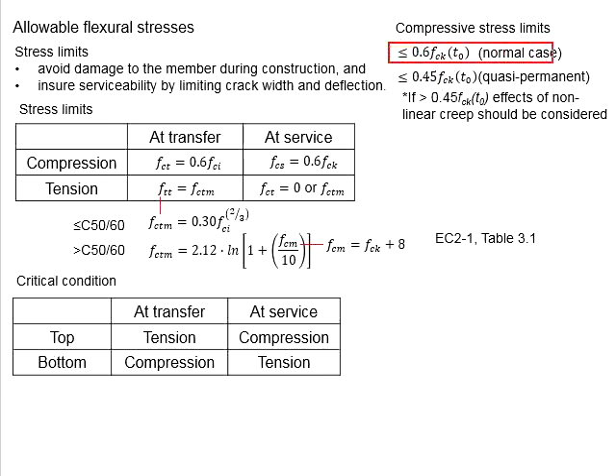In our case, we are referring to the normal case that gives the compressive stress limit of 0.6*FCK at the time of the concrete. FCK is the characteristic compressive strength of the concrete, and the compression stress limit is limited by 60% of its characteristic strength at that instant. This 0.6 is probably the factor of safety or factors that take into consideration the effect of the flexural response. We will always adopt that 0.6 to be multiplied with the FCK of the concrete.